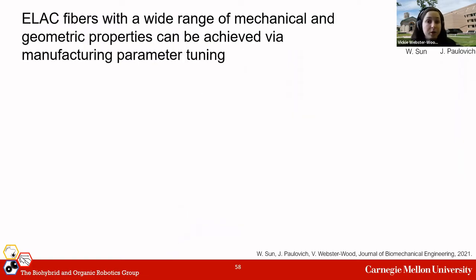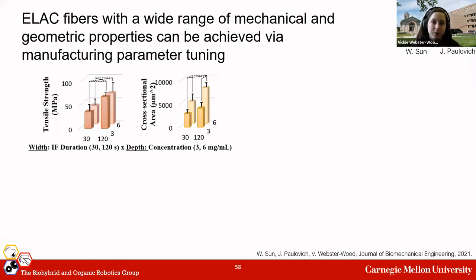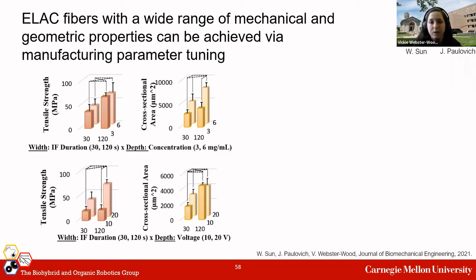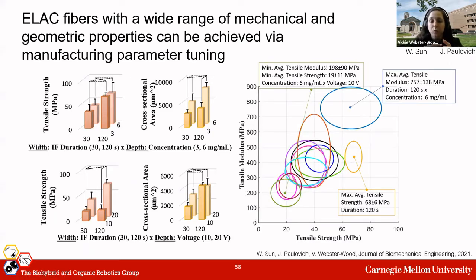For the full study results, I encourage you to read our paper in the Journal of Biomechanical Engineering, but some of the key takeaways include that ELAC fibers made with longer isoelectric focusing duration showed significantly higher tensile strength, failure strain, and a larger cross-sectional area. And ELAC fibers made with lower isoelectric voltages exhibited significantly lower tensile strength, modulus, and a smaller cross-sectional area. We also see joint effects from a number of these different manufacturing parameters. And what this does is it allows us to really tune the mechanical properties of this material across quite a wide range of tensile modulus, tensile strength, and diameter.